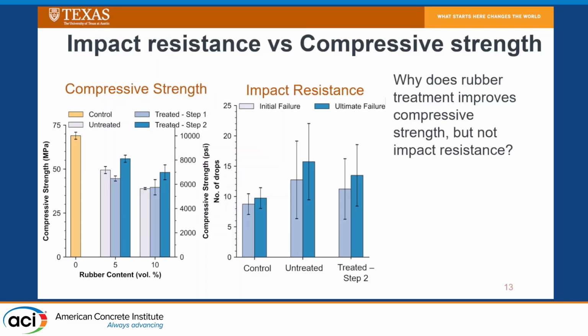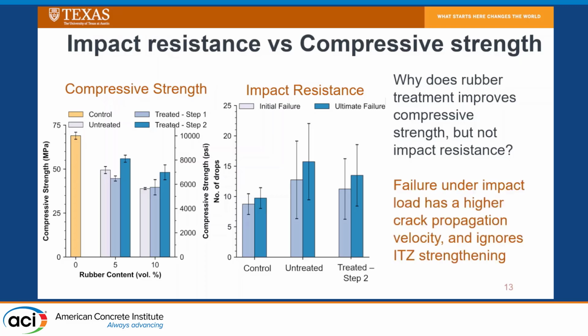So the question here that we were thinking about is, why does the treatment process of the rubber improve compressive strength? Which is great, right? Because that was our goal. We wanted to increase compressive strength. But why don't we get the same effect when we look at doing our treatment process for our impact resistance? So why do we not see a big difference once we start treating the rubber with respect to impact? And the major reason why we think this is the case is due to the differences in failure